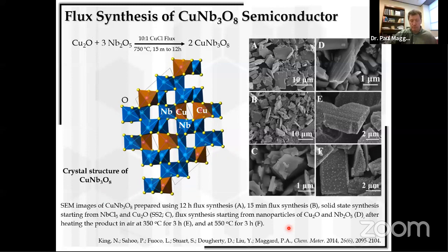We've done the same thing with many other copper 1+ oxides. And in fact, copper 1+ semiconductors, this is a highly active field, with a lot of people working on the delafossites, crystalline structures with copper 1+ in them, and many others. And so here's just one more example of the different crystalline structure with the 138 composition now with niobium oxide rather than tantalum. And the reason we went to the niobium oxide is now we have a much smaller band gap because niobium d orbitals are much lower in energy.